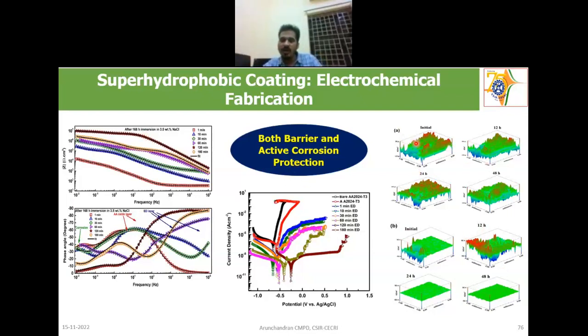And this is the anodized surface without any coating. If I do the SVET mapping, you can see that at various places anodic activity is happening and cathodic activity is happening. The red color represents the anodic activity, the blue color represents the cathodic activity, and the green color is the electrochemically neutral area. As the time increases, in some areas it stopped and in other areas it is increasing, and everywhere it is happening, and the cathodic peak is also higher. So it's a fully corroding condition.